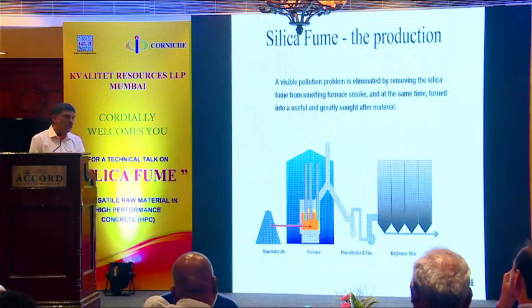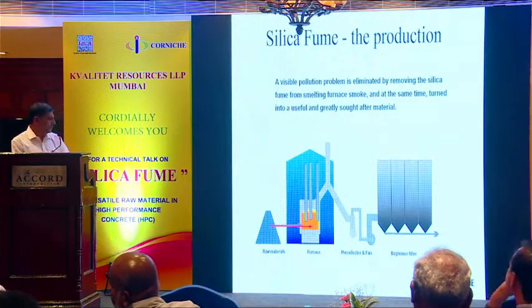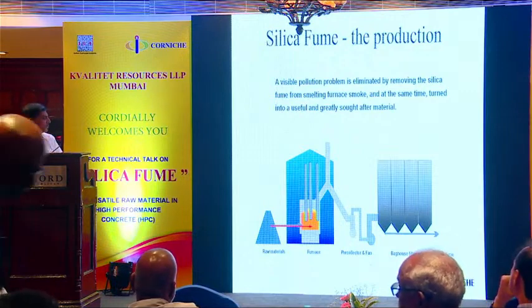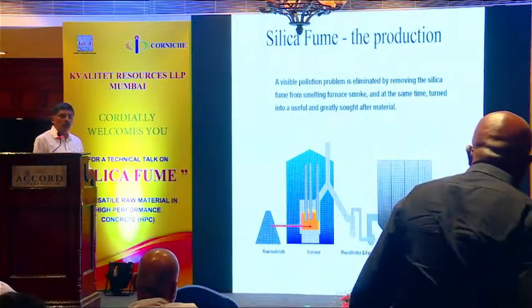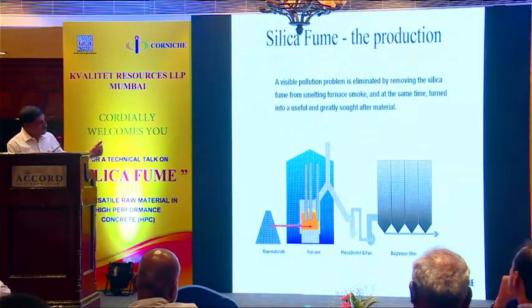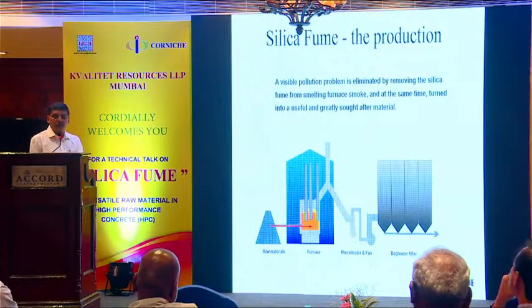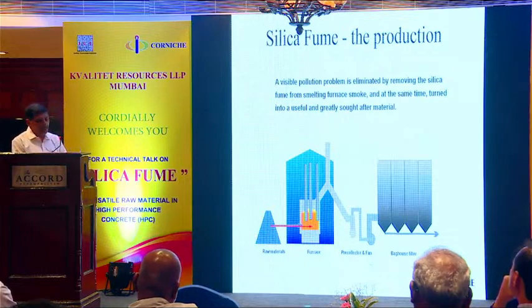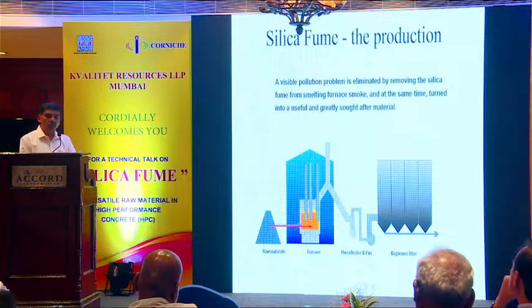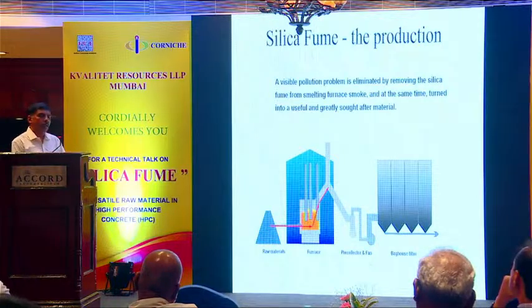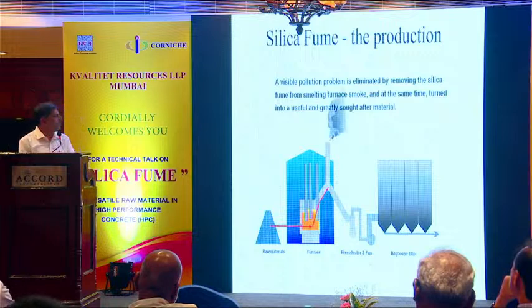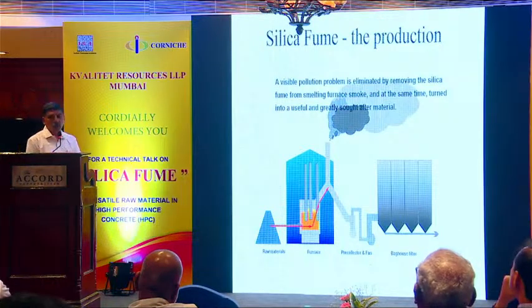Raw materials are quartzite and the black materials. Quartzite is crystalline silica, and black materials are various forms of carbon: coal, charcoal, wood chips, coke, semi-coke. Smelting happens around 2000 degrees. It's a two-phase reduction. SiO2 gets reduced to SiO, and SiO further gets reduced to metallic silicon. And since it's an open-top furnace, the intermittent SiO comes in contact with atmospheric oxygen, and it gets oxidized to SiO2 again, amorphous SiO2, which would have gone out as a pollutant out of the chimney.